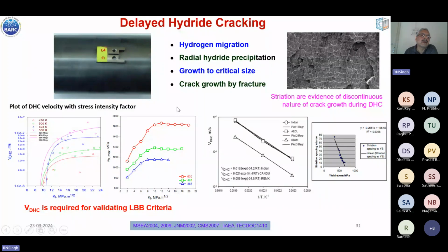If you see, this DHC behavior is characterized by two important parameters. One is the delayed hydride cracking velocity, another is the threshold stress intensity factor. If you see the plot of delayed hydride cracking velocity as a function of stress intensity, a threshold value is observed below which this delayed hydride cracking velocity is insignificant. And as you increase the stress intensity, initially DHC velocity increases, and then we attain a plateau region where this DHC velocity is independent of stress intensity factor.